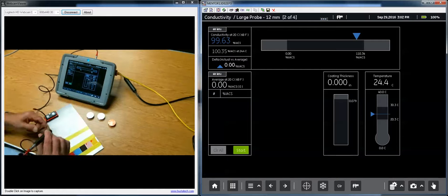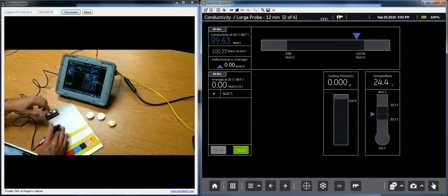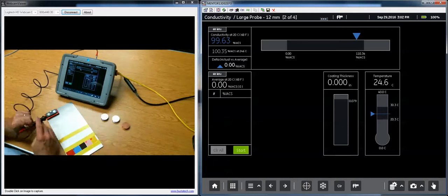99.6. Okay. Now, as we talked about before with the lightning strike inspection, if you look at the procedures that come from Boeing or Airbus, the airframe manufacturers, because materials vary a bit from plane to plane or from area of the aircraft to area of the aircraft, the way the procedures work for inspection is you go to a known good area of the airplane. So you pick a part of the plane that is similar in construction to the part that you are suspect of, that you want to inspect.